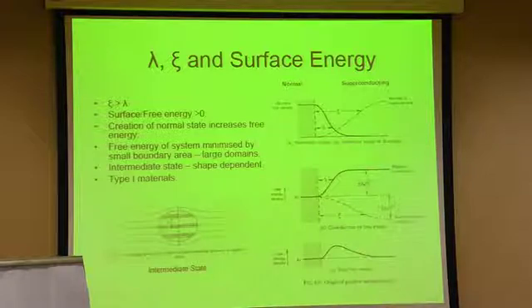Now, the free energy density. What do we have? We have a positive energy from the magnetic contribution, and this is 1 over 2 mu 0 Hc squared. This is how it varies from maximum to zero, over the distance lambda for the magnetic field. Now, why do we have superconductors? When Cooper pairs are formed, the free energy in the superconducting part is smaller than the free energy of the metallic, the normal part. So obviously, the free energy in the superconducting part is negative relative to zero.